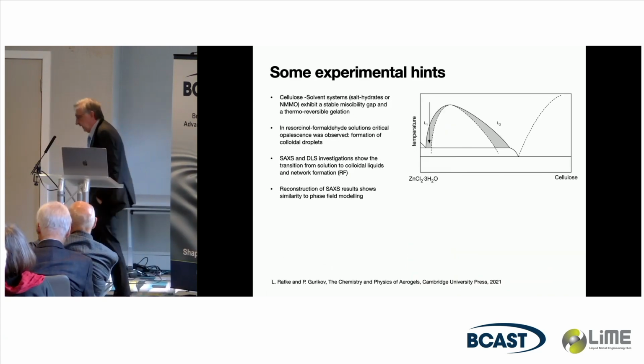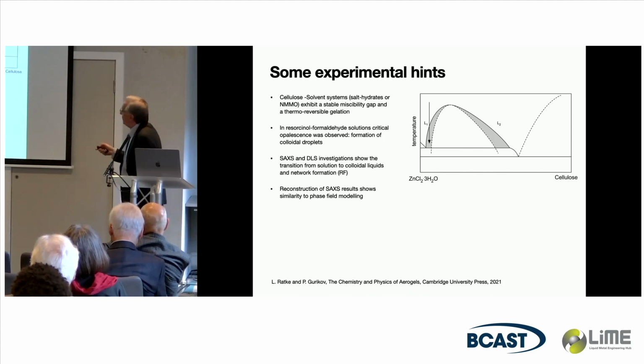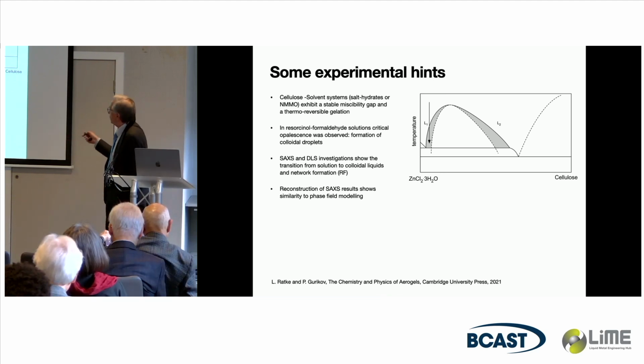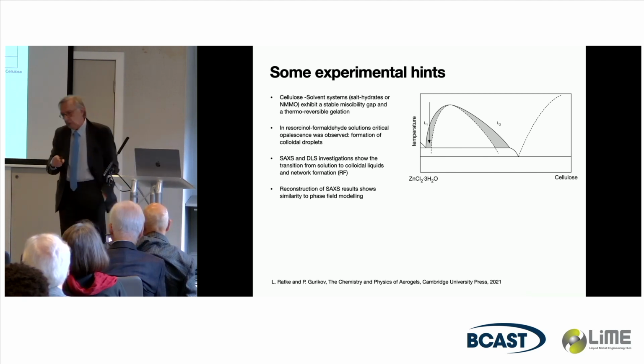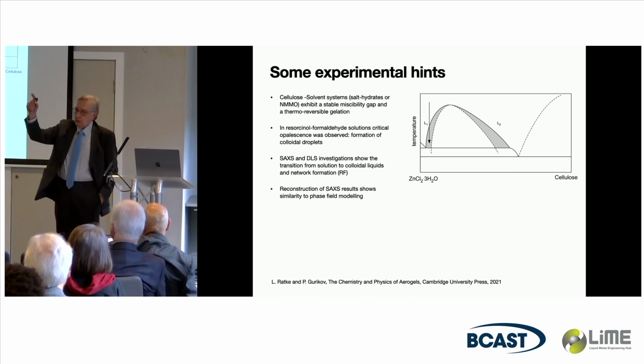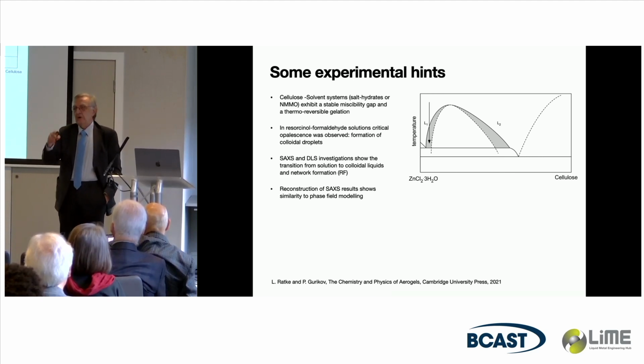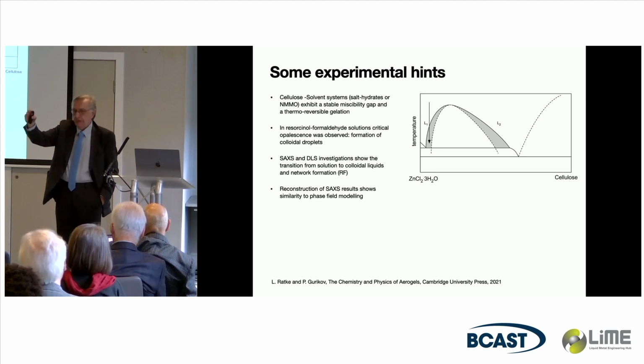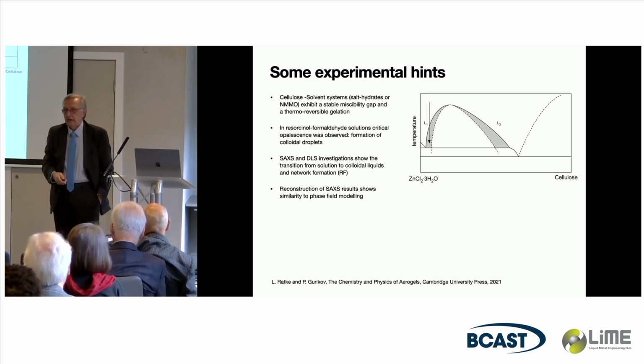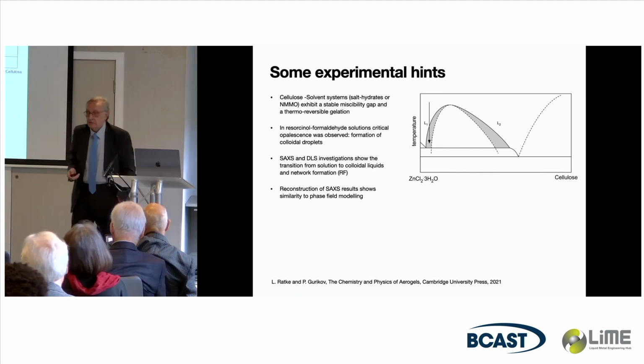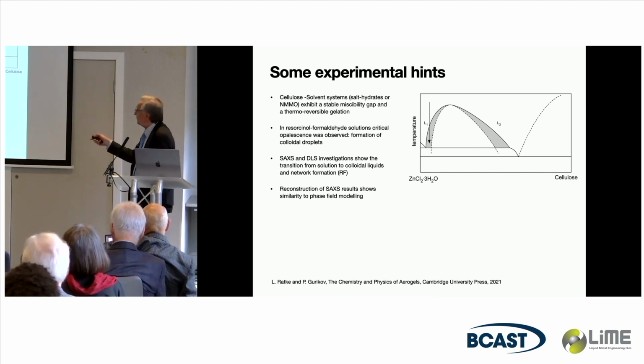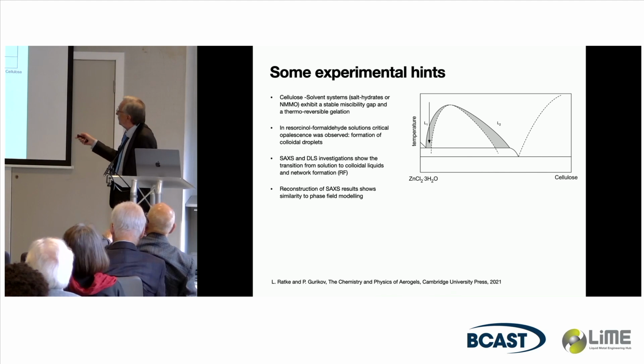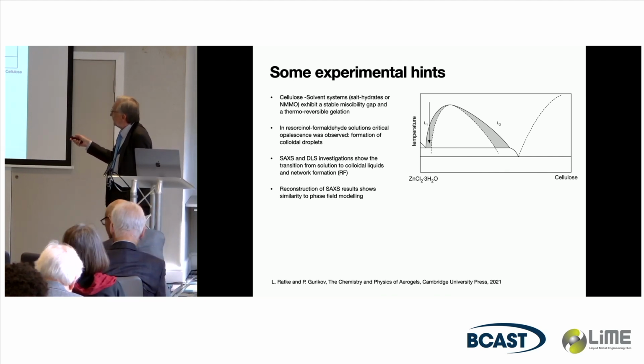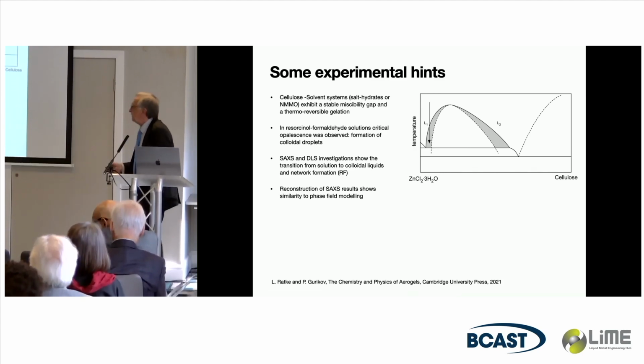So, some experimental hints why I think this is phase separation. This is an estimated phase diagram of zinc chloride trihydrate with cellulose. That is a solvent for cellulose. And if you do an experiment, so you go in a viscometer, you heat it up, let's say to 90 degrees, cool the solution down, you find it gels at around 40 degrees centigrade. You heat it up again, you dissolve everything, and you cool it down, you find again it gels at 40 degrees. So it's reversible. Cellulose seems to be a reversible system with an upper critical point. The same you would find also when you do not use salt hydrates, but methyl morpholine oxide, which is also a wonderful solvent for cellulose.